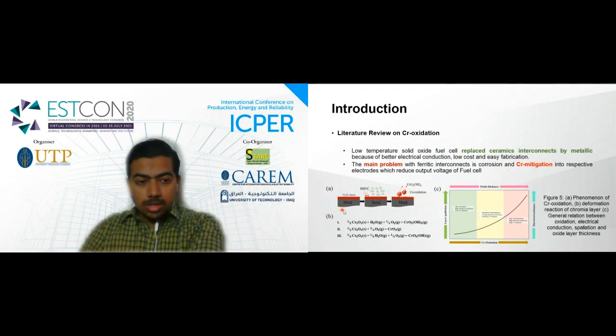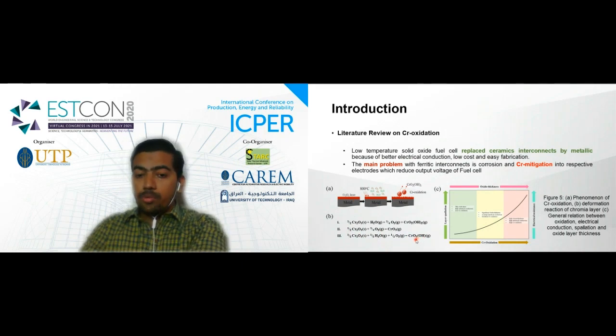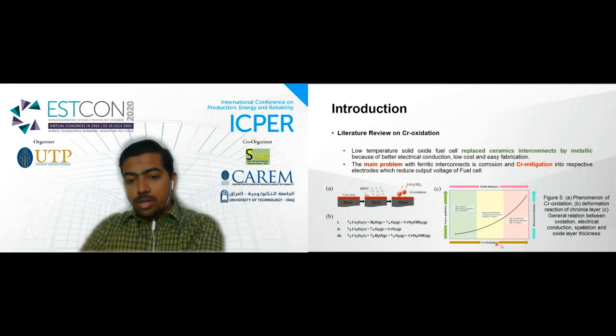You can see over here, almost every steel has a chromium layer at the top surface. When it is heated in the SOFC environment, the chromium layer reacts with the oxygen and water molecules to form chromium hydroxide, which is volatile in nature. It penetrates into the respective electrode and decreases output voltage. As the chromium oxidation increases, electrical resistance also increases, which decreases the fuel cell efficiency. So we need to control it.